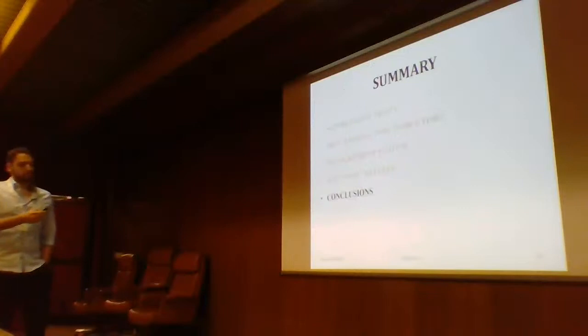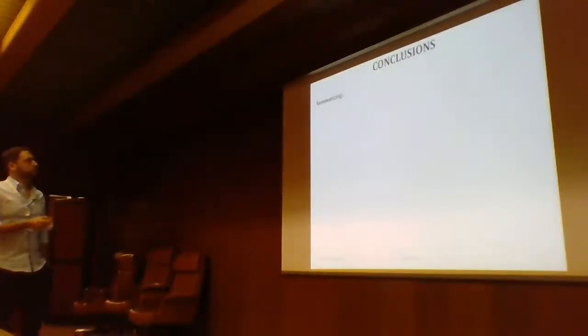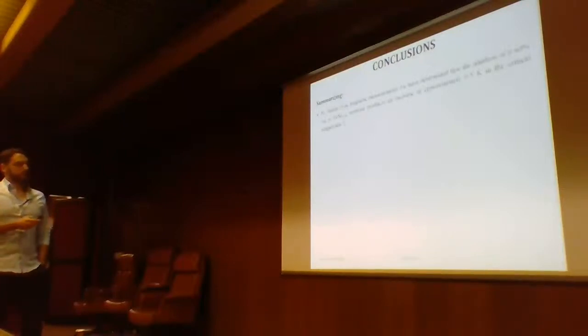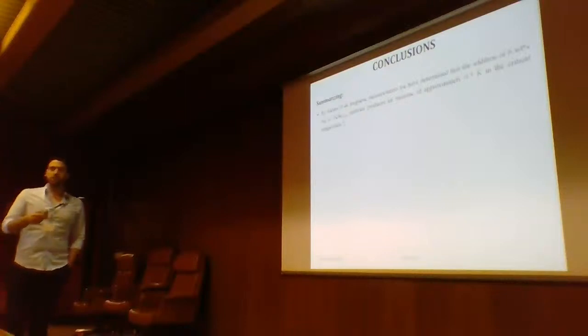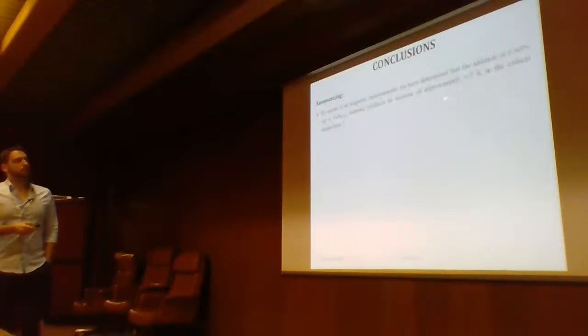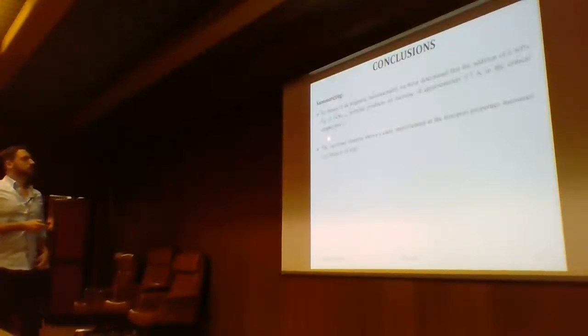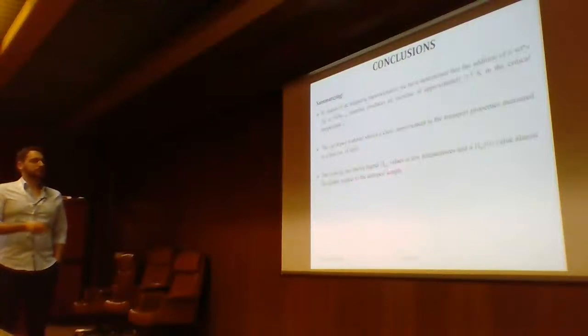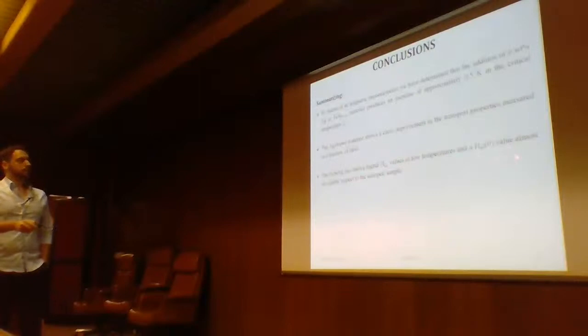So, the conclusions are shown below. In particular, by means of DC magnetic measurements, we have determined that the addition of 6% in weight of silver in our iron selenium material increases the critical temperature by approximately 0.5 Kelvin. The second property we have observed is that the doping with silver shows a clear improvement in transport properties, that is the critical current density of the sample, measured as a function of the field. Moreover, we have also shown higher irreversibility field values at low temperature and also at T equal to 0 Kelvin, where the irreversibility field was almost double with respect to the undoped sample.